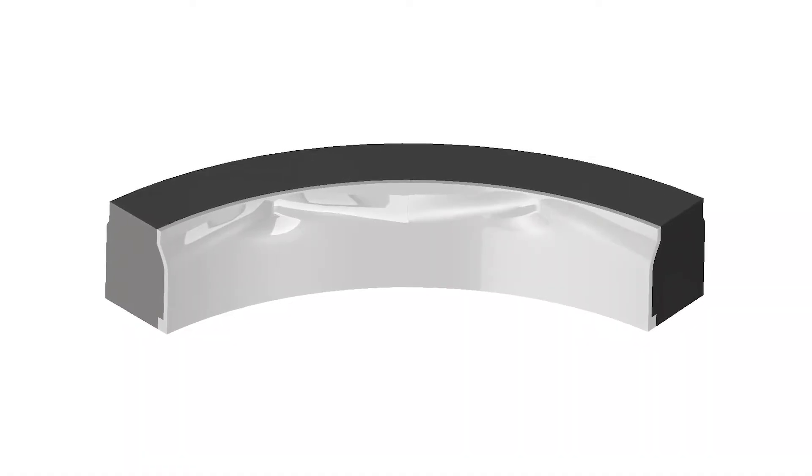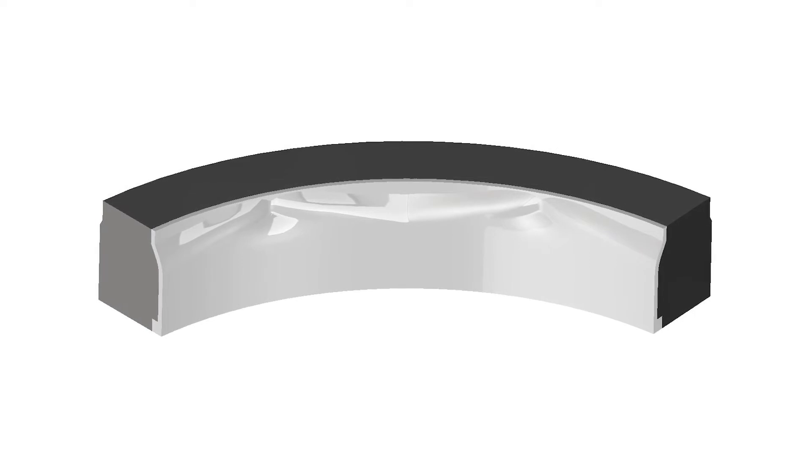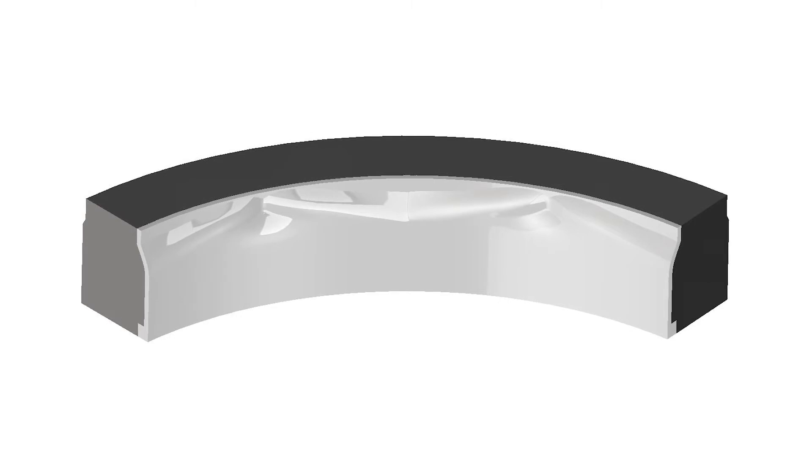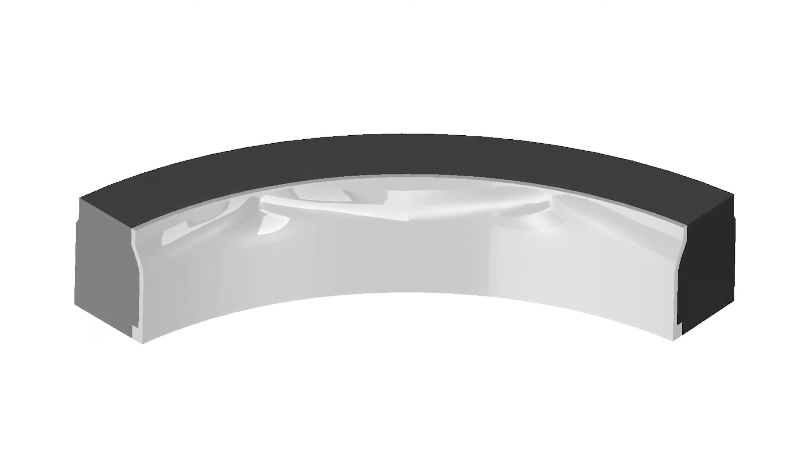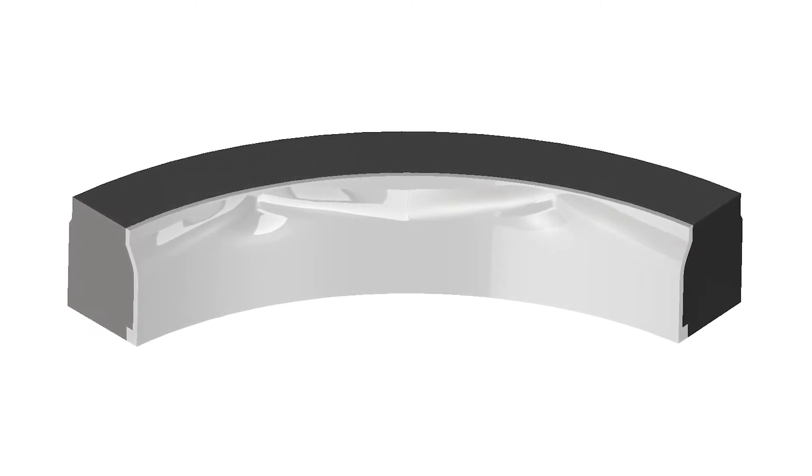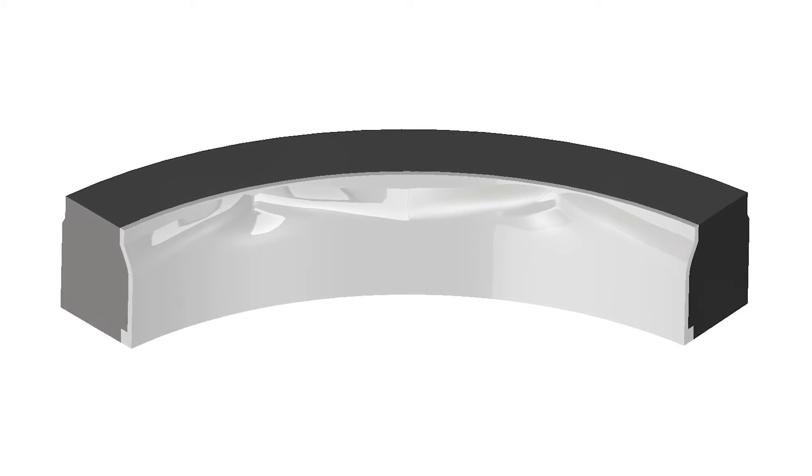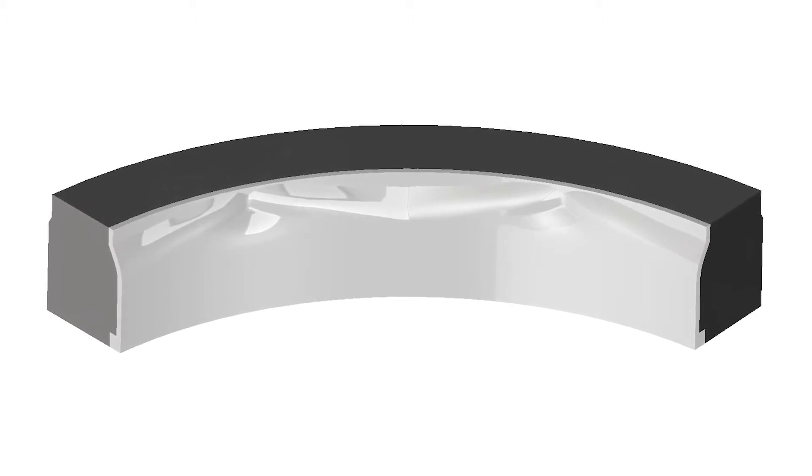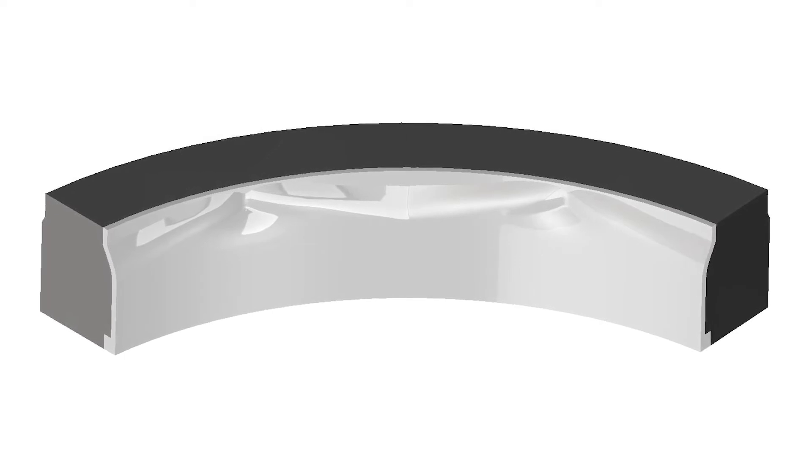This was the inaugural test of our super-wide plastic-lined seals, which were designed for extreme pressure operation. Under the same test conditions, the previous generation seal only lasted about 120 hours. The increased lip-width and high-modulus plastic of the super-wide seals allowed us to reach the 300-hour operational goal.